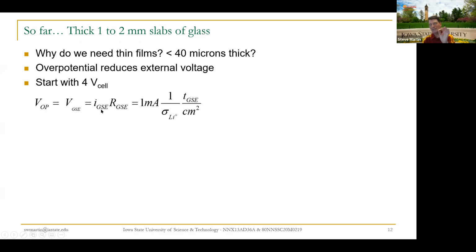In this case, it's not the electrons in the exterior circuit, it's the ions through the middle, through the solid electrolyte. So it's the ionic current through the glassy solid electrolyte multiplied by the resistance of the glassy solid electrolyte. But Ohm's law still holds. So let's choose 1 milliamp as a typical mid-range current, a little lower in some applications, a little higher in some applications. We'll choose 1 milliamp.